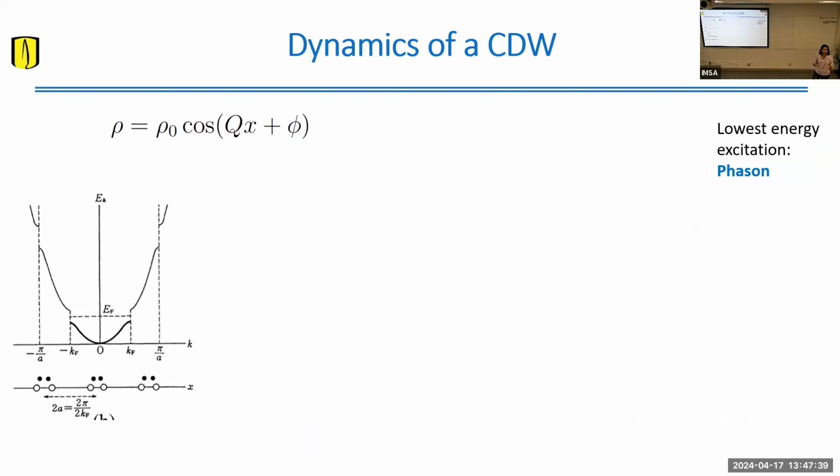This modulation also comes with an anomalous phonon structure in which you will have a Kohn anomaly, which is the softening of a phonon in the material, which also modulates the periodicity of your lattice. But I'm giving you the flavor of the electronic side of it because I want to aim for some interesting topological states in the electronic structure and how that correlates with the charge density.